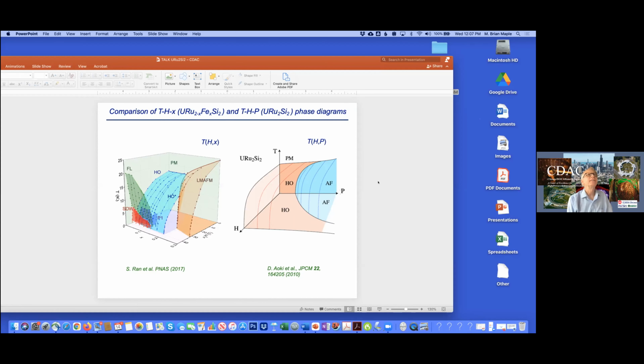More questions or comments? Oh, Brent, go ahead. Thank you, Russ, and thank you, Brian, for this very interesting and extensive talk, and a lot of data here. I'm thinking about this chemical substitution and the effect of chemical pressure for the iron and osmium substitutions for the ruthenium, where you have a different average change in the unit cell parameter with the different substitutions, which would seem to rule out parallel to pressure. But one of the things that would be similar at these low concentrations of solutes is that you'll have some unit cells that are off the average lattice parameter and some of them that are closer to the lattice parameter. And so there may be a distribution of strains effectively, and some of the phases may be more or less sensitive to the strain distribution. Does that sound at all plausible?